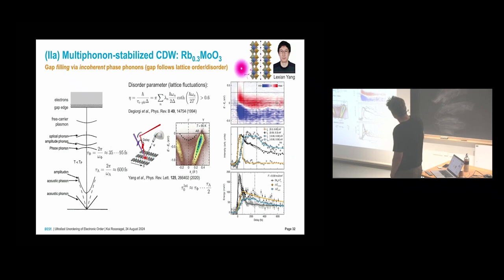So then you can integrate the intensities, and you can really see, this blue transient here, how the intensity in the gap rises on a time scale which is much faster than this thing here, which is the first maximum of the coherent oscillation. So here you really have a scenario where you can quench a gap by filling it in much faster than the coherent vibration. This is then an order-disorder type transition happening on a characteristic time scale of these phase phonon modes, which again have higher energy than the amplitude mode and thereby shorter times.